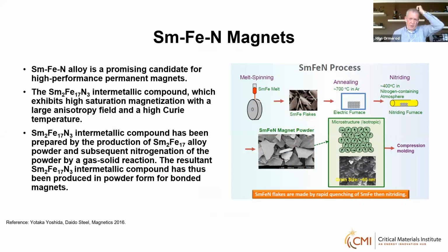A quick word about samarium iron nitride. Now, the Sm2Fe17N3 compound was discovered shortly after the discovery of the Nd2Fe14B phase back in the 1980s. However, for a variety of reasons, the commercialization of this material has been limited. Again, the process starts with melt spun materials. The powders are annealed and then nitrided at a relatively low temperature. The powders are then used in bonded magnets.